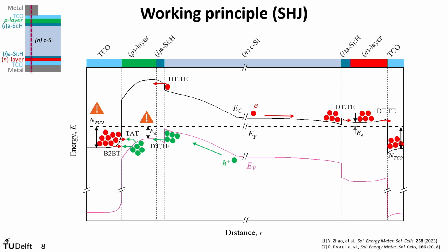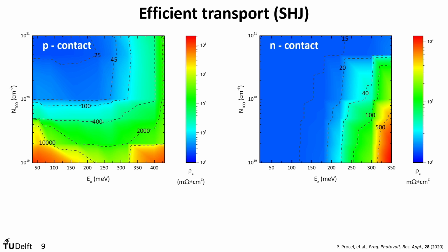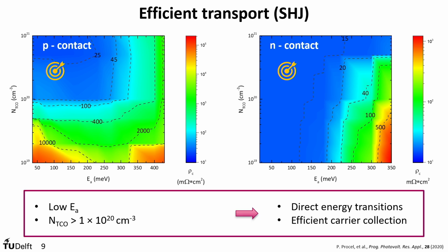So in these two heat maps, P-type contact and N-type contact, we run essentially a variation of activation energy versus carrier concentration in the TCO. And every colored pixel is the information related to the contact resistivity of that stack when we consider a TCO and the doped material on top of the passivating layer. And you see here that, of course, in both cases, we have a kind of target that looks into relatively low activation energy and a relatively high doping carrier concentration in the TCO.